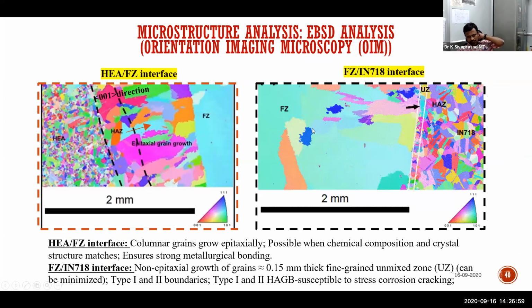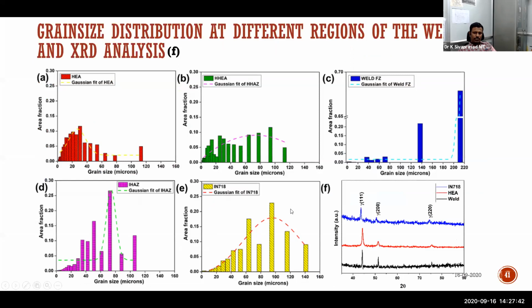Again, here also orientation imaging microscopy was done. This unmixed zone, one can clearly see this. This is the unmixed zone. Then here HAZ was clearly seen, and almost all grains were growing in the 001 direction. This is the epitaxial growth direction. That is evidence. So again, with orientation imaging microscopy, we have analyzed so many things metallurgically. I just don't want to bore you with the metallurgical aspects related to it. With this kind of gradual transition, it is supposed to give good properties in these microstructures. High angle boundaries and low angle boundaries, everything you can calculate, associated with this one.